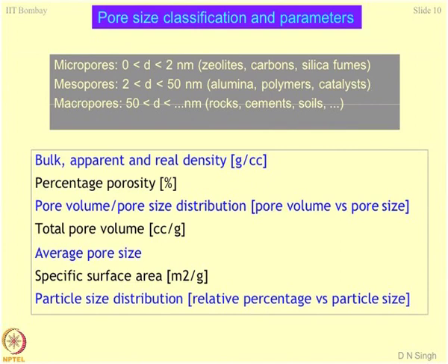And macropores are the pores which you normally talk about when you do your porosity tests to obtain the porosity. That is where I say you only talk about one-third or one-fourth of the porosity of the total system, ignoring the microporosity and mesoporosity, for which you require either helium gas or mercury, so that under pressure these fluids will enter and reach these pores. Water molecules cannot reach these pores. That is why you require non-wetting fluids like mercury and helium gas to do pore structure analysis.